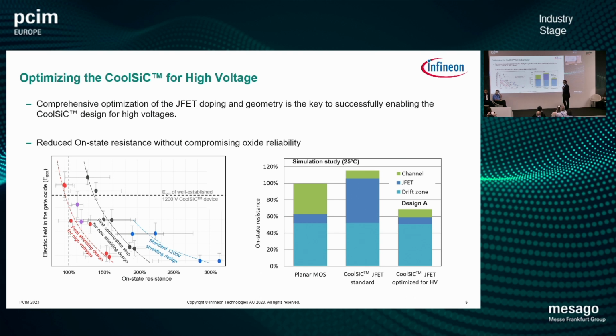You can clearly see the contribution of the JFET, which means more JFET resistance in the structure, and we would end up with a higher RDS(on) if we kept the same JFET structure. With the optimization of the implant, we have a high voltage trench MOSFET where we are able to really bring down the losses in the JFET, almost to the level of a planar MOSFET. This was considered the base for our next 3.3 kV silicon carbide MOSFET.